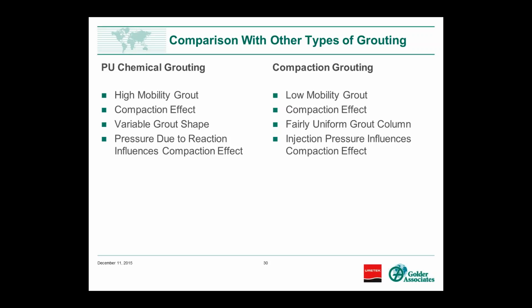The polyurethane is definitely more high mobility. The compaction grouting is a very low mobility grout, and with the conventional compaction grouting, you end up with sort of a column of bulb-shaped concrete inclusions. The shape of the polyurethane is definitely a little more variable.